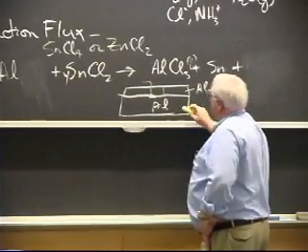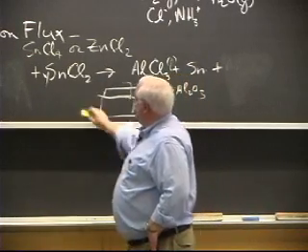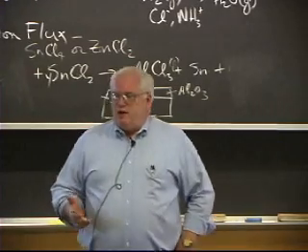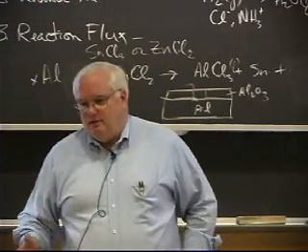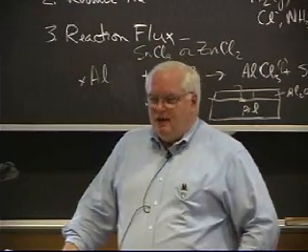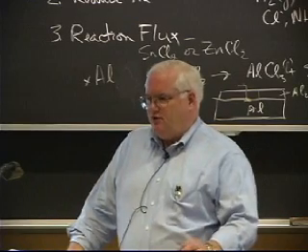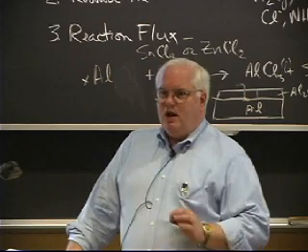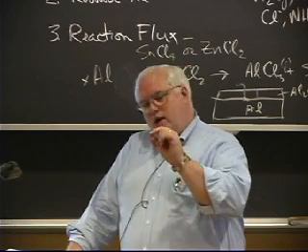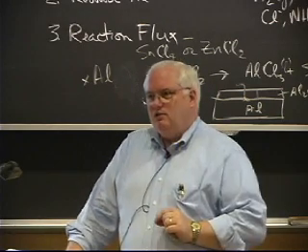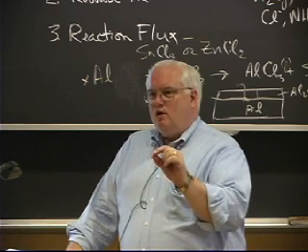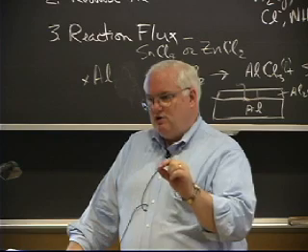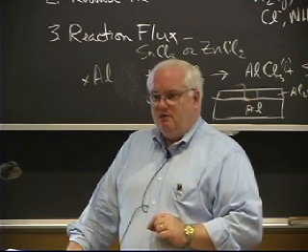And in fact, the big problem with all of this is these tin chlorides and zinc chlorides tend to be very hygroscopic. In fact, they're so hygroscopic, they're called deliquescent. Anybody ever heard deliquescent before? Something is deliquescent if you took a crystal of tin chloride and put it on the table here, and came back half an hour later, and I'm talking about something the size of a single grain of salt, you would find a drop of water about the size of, well, probably a BB, and if you came back 5 or 6 hours later, it might be the size of half a small pea.